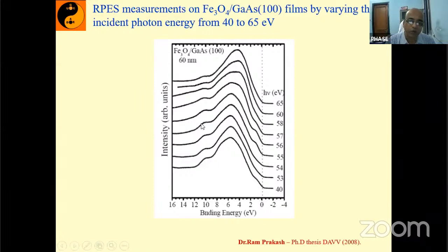Also, this peak is varying as a function of position. So this kind of thing one can get, and one can do the fine analysis of this, and very high quality research can come out of it. This is one of the examples I have given, on the Fe3O4 film on the gallium arsenide substrate. This is the resonant photoemission spectroscopy kind of thing one can do using the synchrotron base.